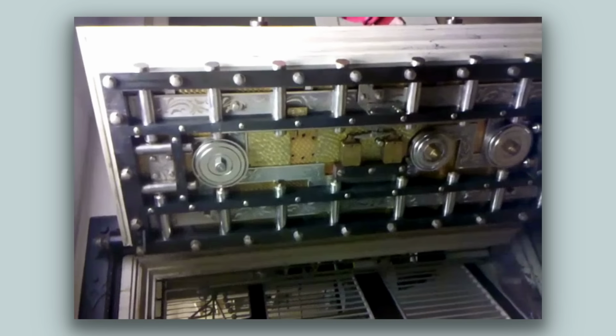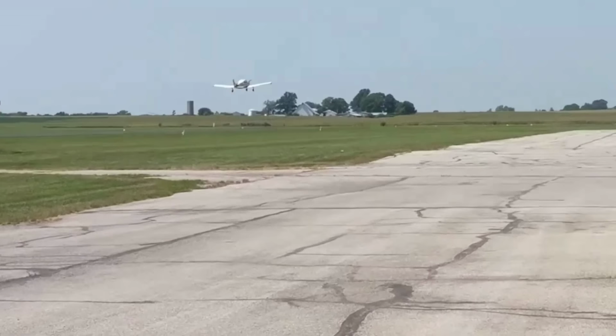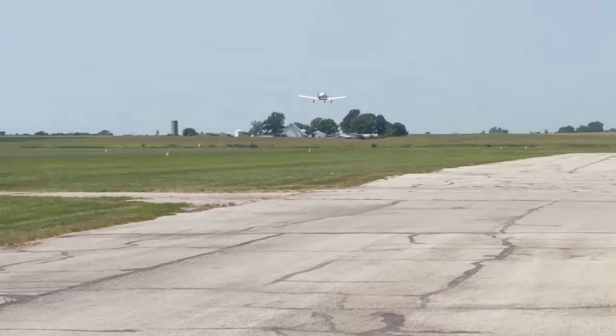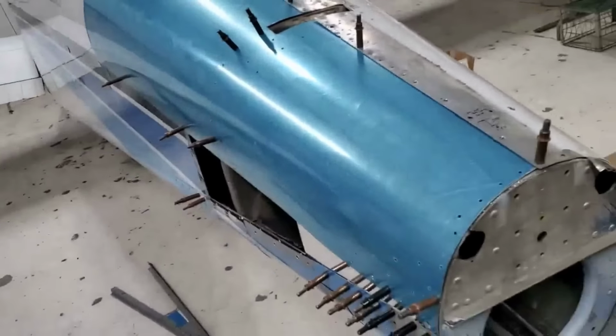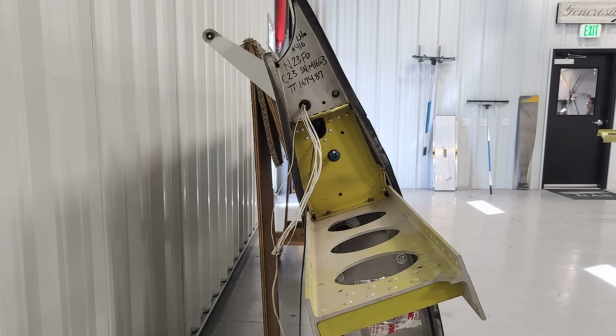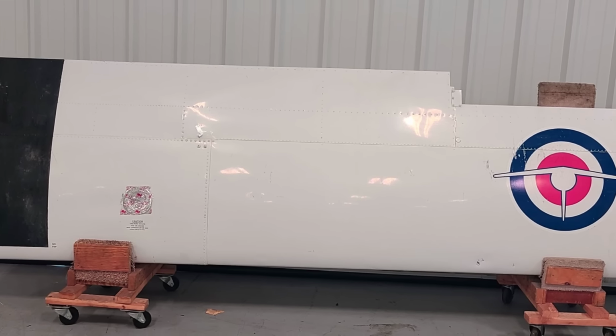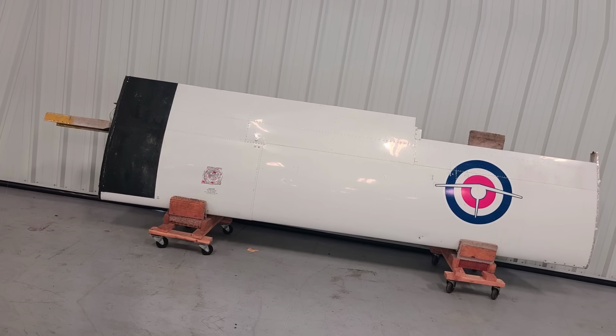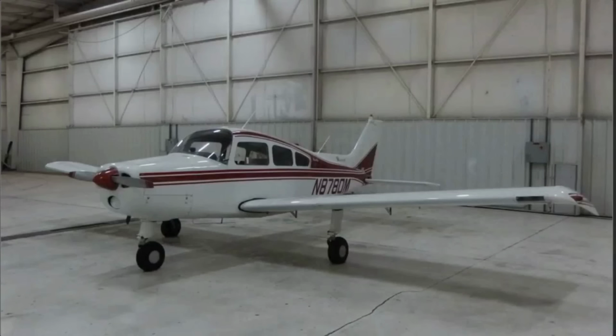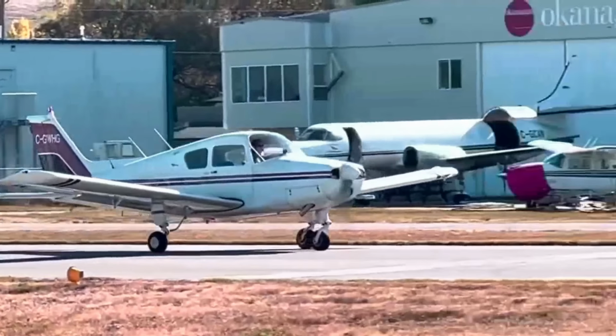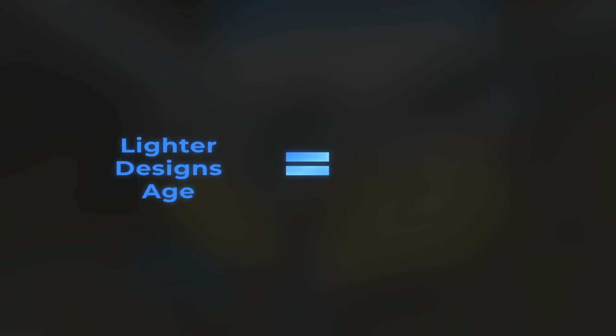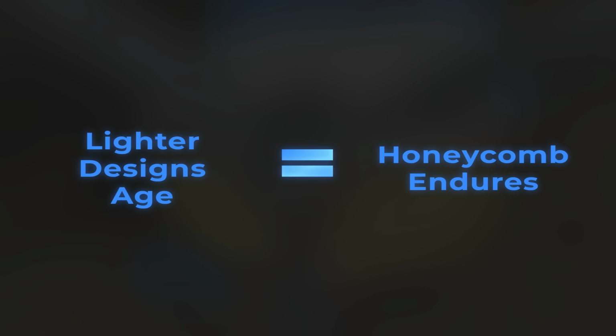In practice, this makes the wing heavy for its size, but nearly immune to local dents and fatigue cracks. Owners who have cut into these wings for repair often find the honeycomb core intact after decades, the adhesive still holding tight, the aluminum barely marked by time. It is a kind of overkill, extra weight traded for a vault-like solidity. The price is paid at the fuel pump, but the reward is a wing that shrugs off abuse and keeps its shape long after lighter, more efficient designs have started to show their age.